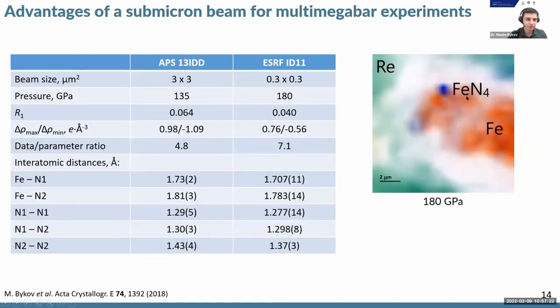To show you some numbers, we can compare the structural refinements performed at the microfocus beamlines and the standard dedicated high pressure beamlines. And we see that with the microfocus beam, we can really locate the tiny grain of FeN4 in our sample and collect very high quality data with better residual factors. And what's more important for the chemists is the high precision on the interatomic distances and angles, which allows us to discuss the chemistry of these compounds.